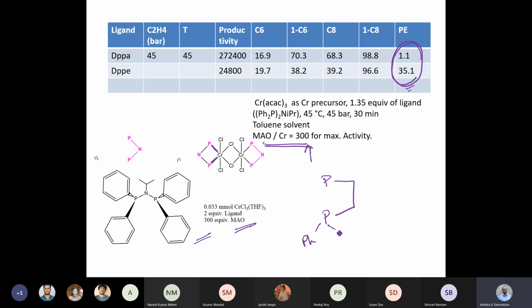PCH2CH2P, PH. The only difference between the two, PNP, PH, the two is the fact that you have one atom less, but I should not overlook the fact that this nitrogen has got a lone pair which is partially delocalized with this phosphorus. So you do have a little bit of population of the phosphorus higher lying orbitals or the sigma star orbitals, resulting in a different coordination behavior for the phosphorus